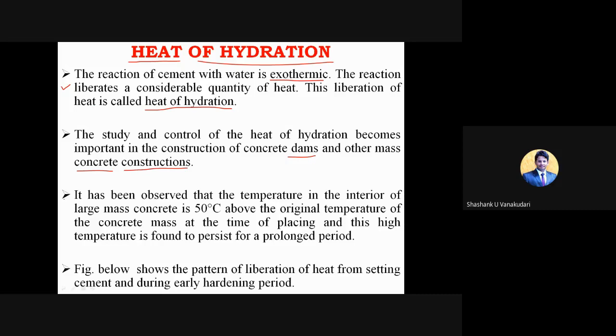And here you can see the facts behind this heat of hydration. It has been observed that the temperature in the interior of large mass concrete is 50 degrees Celsius above the original temperature of the concrete mass at the time of placing, and this high temperature is found to persist for a prolonged period. It's nothing but this: when you add water to the cement, the chemical reactions that take place liberate some amount of heat. Because of that heat, the temperature within the concrete structure increases 50 degrees Celsius above the normal one.